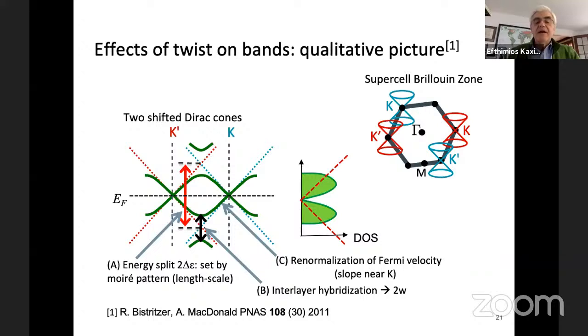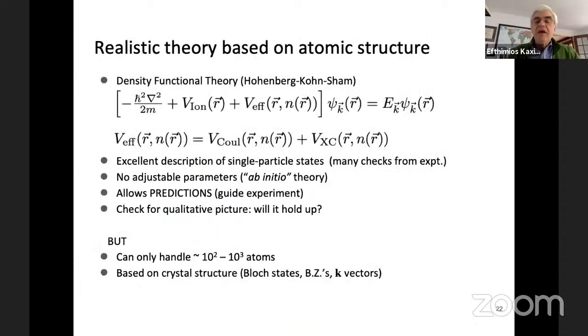So here's the density of states again. So this is density of states as a function of the energy. And this is the zero, the Fermi level. These dashed lines are the cones of the graphene layers, the individual layers. And these are the density of states of the new bands formed by the repelling, the splitting of the individual graphene layers.